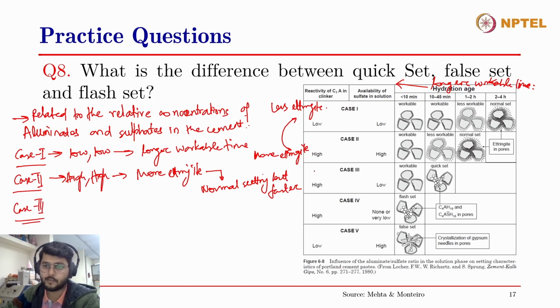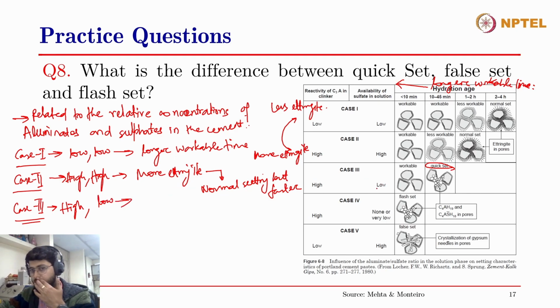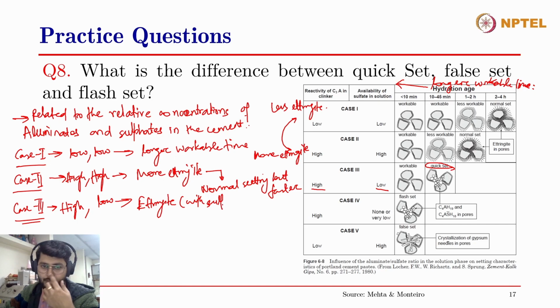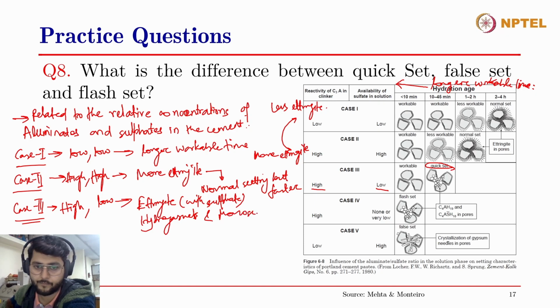Case 3 leads us to what we know as quick set. When the C3A availability or the reactivity is high, while there is still sulfate in the system, but in low quantities. If the quantity of sulfate is low and the availability of C3A is high, then it will form a quick set. Quick set meaning that some of the aluminate will form ettringite with sulfate, but with time, when the sulfate gets reduced, it will form hydrogarnets and monosulfate products as well. So that will lead to a quick set.